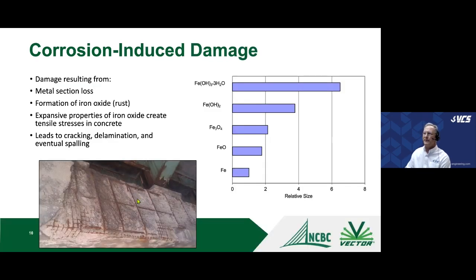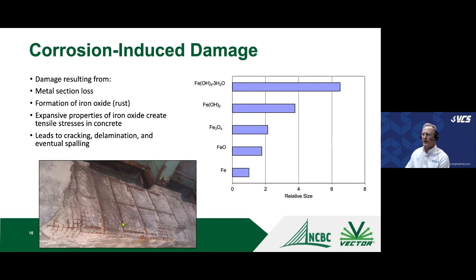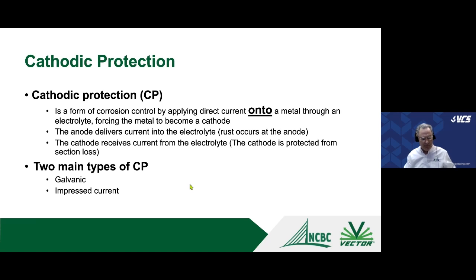The damage occurs because the corrosion products swell. Relative to iron's base volume of one, the oxides range from about 2 to 7 in volume. Typically you'll see an expansion of around 3 to 4 in atmospherically exposed concrete, causing spalling and delamination. In this example the structure was shotcreted — they just covered up the spall without addressing the corrosion — and it failed again. If you want to do something about corrosion, cathodic protection is the main tool.